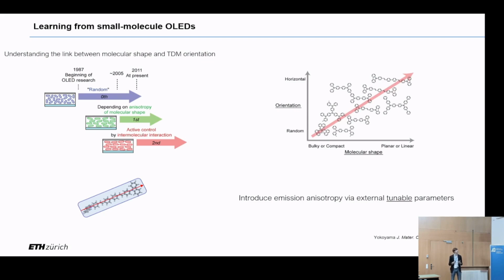And this has to do with a key point, which was the understanding of a link between transition dipole moment orientation and some molecular parameter, like molecular shape. We heard quite a bit about it: molecular shape, moment of inertia, temperature, right? Because now, for example, molecular shape and molecular orientation is something we can control by deposition parameters, temperature, and so on. And at this stage, we started asking the question, can we learn something from it? Can we apply similar strategies to nanocrystals?